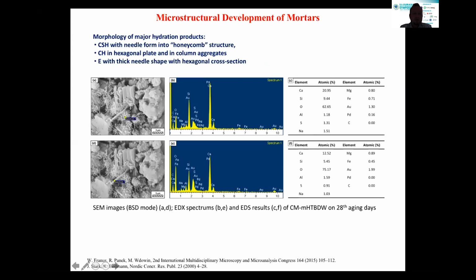These are the SEM images and EDX spectrums taken by scanning electron microscope. Here, we made spot analysis on the honeycomb structure and on the hexagonal plate. The obtained values show the formation of calcium silicate hydrate and calcium hydroxide, Portlandite, I mean. But here we cannot measure the hydrogen element by the EDX spectrum. That's why you cannot see this element on the list.